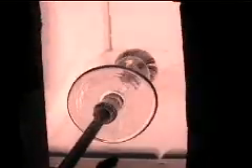The heating process on this takes a little while. We also have to keep the foot hot so it won't check or break or pop on us later on. So everything's got to be kept hot while the top part needs to be reheated to the hottest, because you'll see in a minute this is where we have to flare out the top and make the kind of base for the candle to give it a little definition. I like the bottom and the top to be roughly the same when we get through. It'll almost look like two wheels with an axle on it when you get through, but that just gives it a lot of balance, and that's what we're after right now.